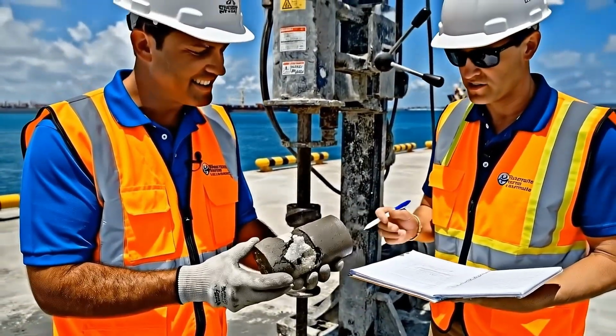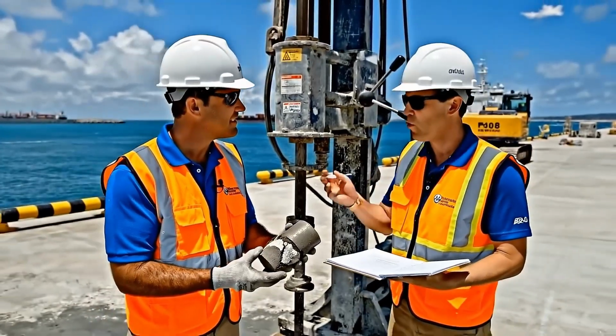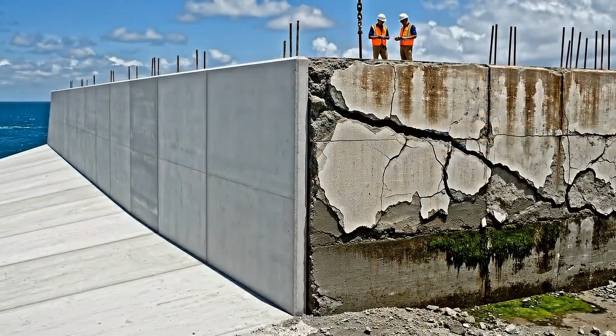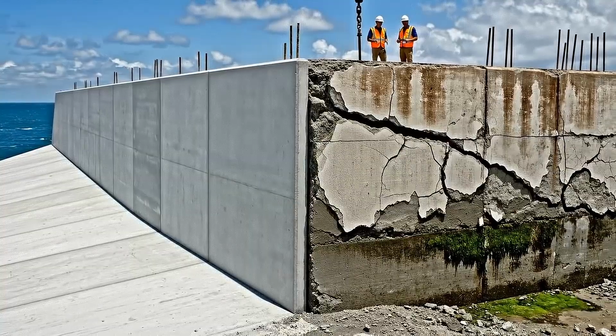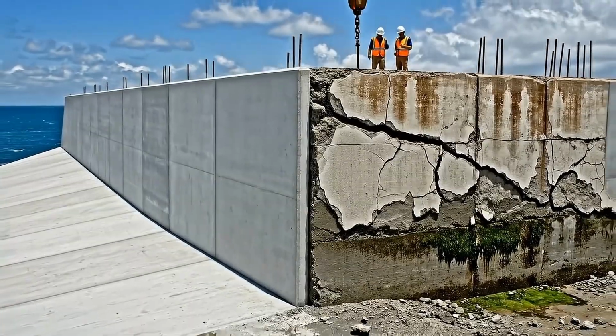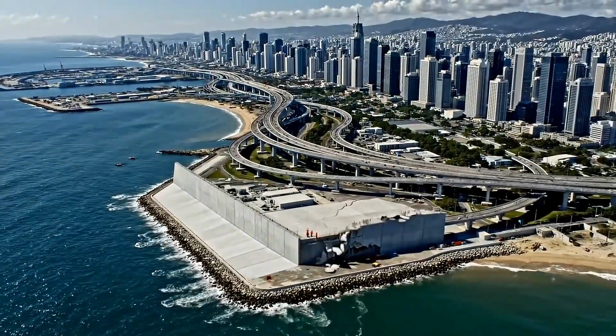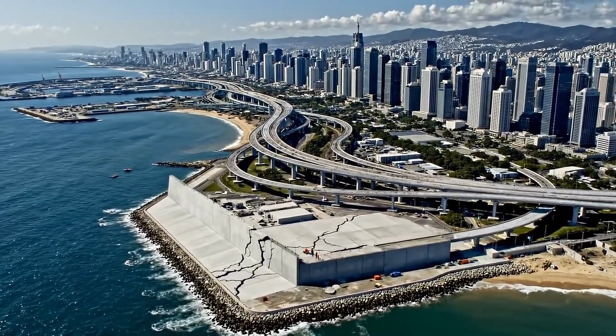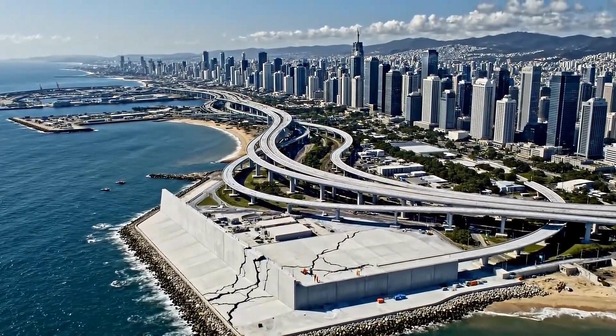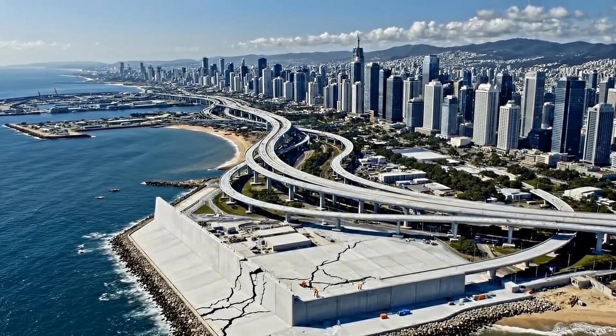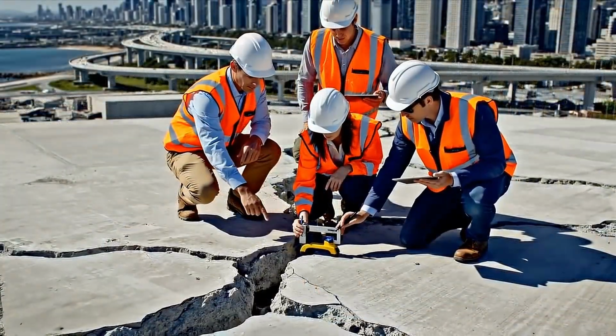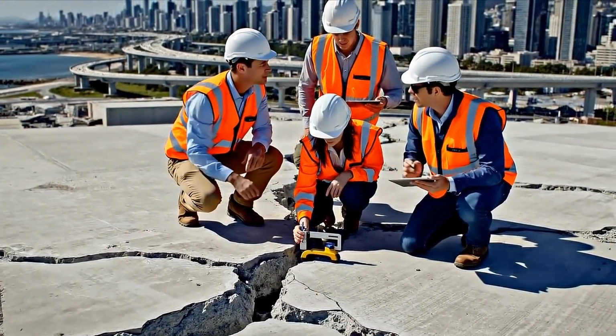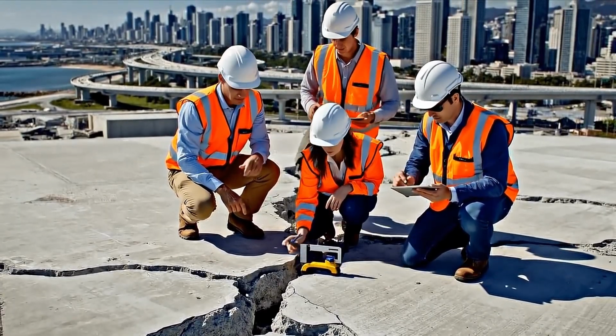The comparison is stark. This new section shows no wear at all, while the 30-year-old Portland cement is already deteriorating significantly. The self-limiting nature of the process is as important as the healing itself. A repair process that continued indefinitely, generating crystalline growth throughout the deteriorating concrete matrix, would be a problem. We're seeing significant displacement. It's past the limit for self-healing options.